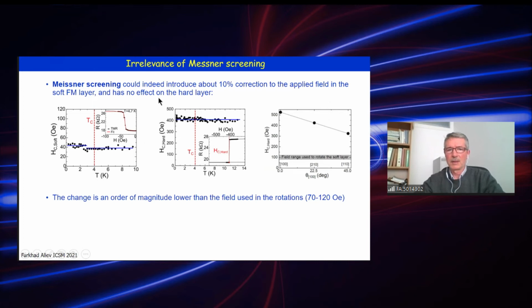So in our experiments, these changes of Meissner screening introduce only 10% correction to the effect.